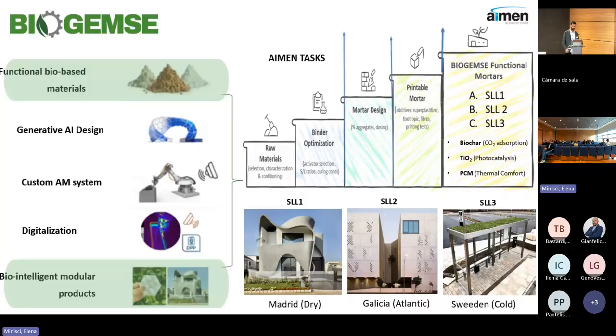So our task can be divided as in the diagram that I show on the right. We start from the raw materials that will be some biomass ashes. In this phase, we characterize through different techniques: chemical composition, crystalline phases, amorphous content, granulometry. After that, we start with the activation. We try different strategies, different alkaline activation with different solid-liquid ratios. Once we have an optimized binder with good mechanical properties and reactivity, we start with developing a mortar. We introduce some bio-based aggregates in order to have a mortar.